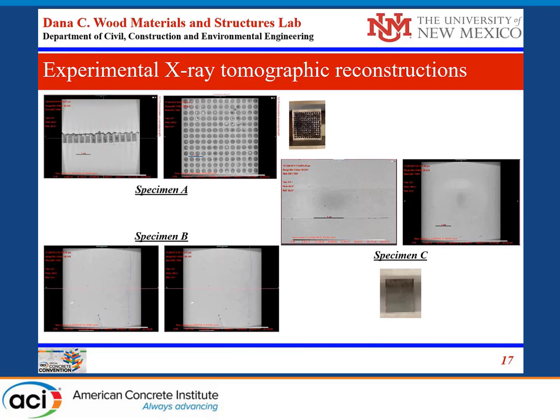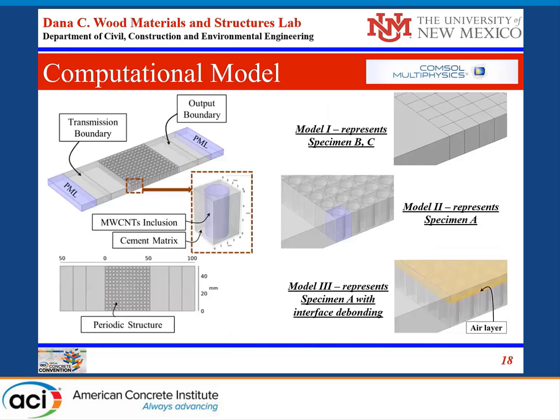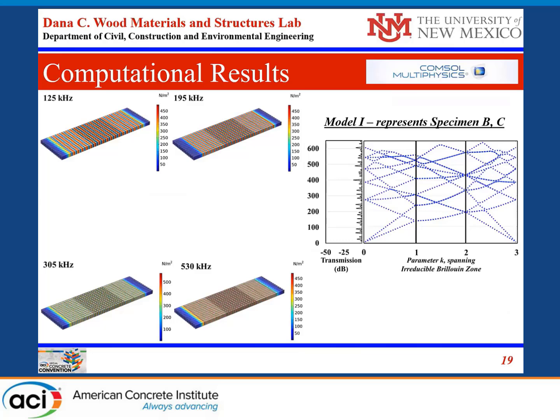To understand the effect of this interface de-bonding, computational models using COMSOL Multiphysics were developed and frequency response analysis was conducted. Three models were created: Model 1 represents specimens B and C — a homogeneous cement block; Model 2 represents specimen A with the periodic structure and no interface de-bonding; and Model 3 represents specimen A with interface de-bonding, to see how the two differ.